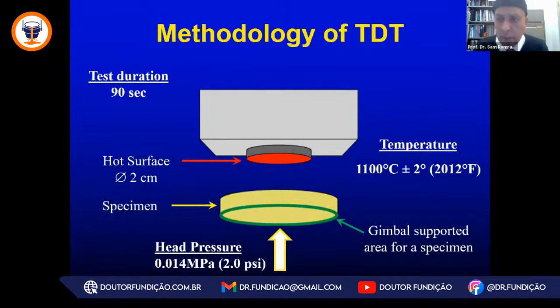But to tell you more about the thermal distortion test, I am using this depiction to show you a hot surface that is 20 millimeters in diameter. And we heat that typically to the mold metal interfacial condition of the alloy. So we can represent aluminum temperatures. In this case, I'm showing you the temperatures around a copper-based alloy, like a black brass or a bronze temperature. But we can get up to iron temperatures. Unfortunately, at this stage, we are limited to iron temperatures, and we are developing technologies around the hot surface to get to steel temperatures, but we're working on that.